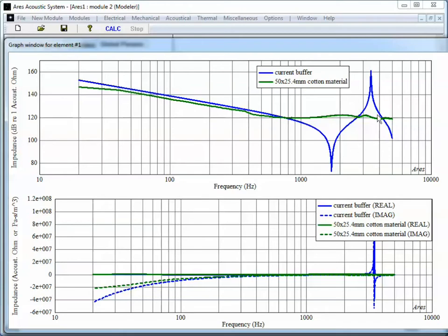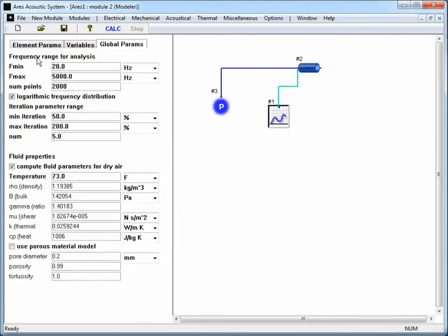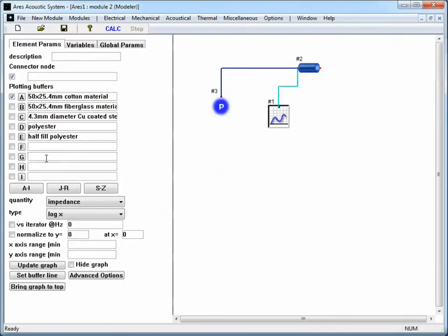We're seeing the quarter wavelength and half wavelength resonances, which have been damped due to the porous material. And at low frequencies, we're seeing the stiffness effect again. However, the stiffness of the air-filled volume is higher than the stiffness of the porous material-filled volume. This is due to the isothermal compressibility that was discussed in the previous video. So I'm going to go back to the model and copy air-filled into buffer G.